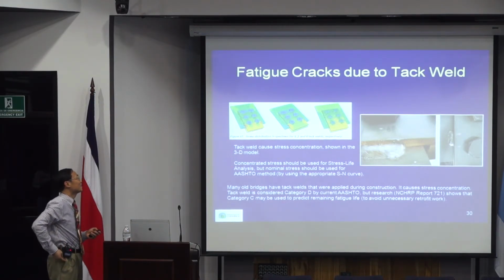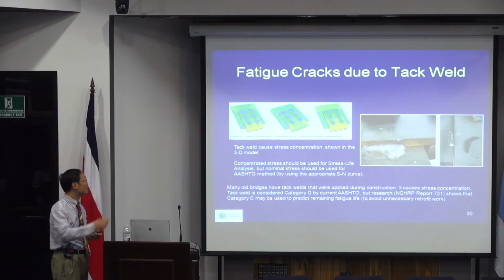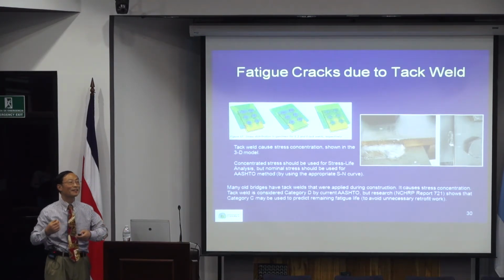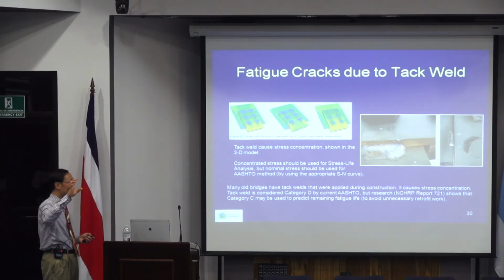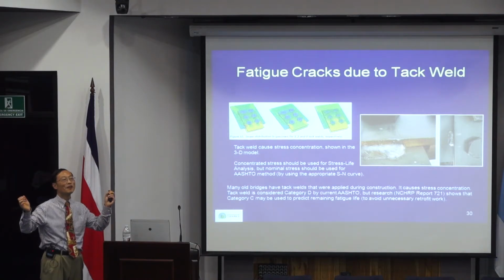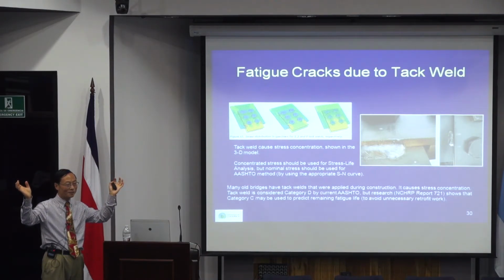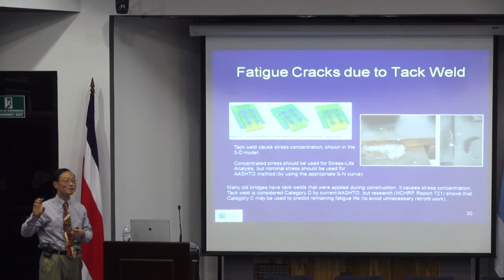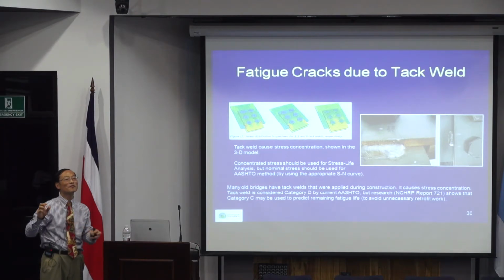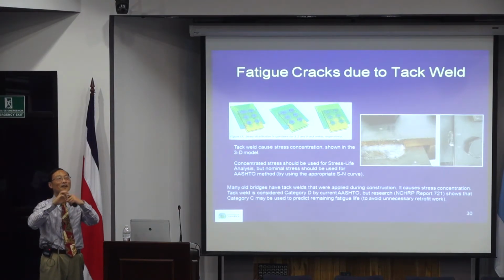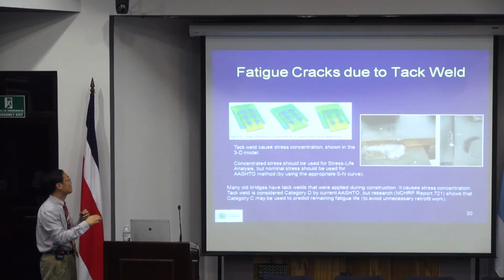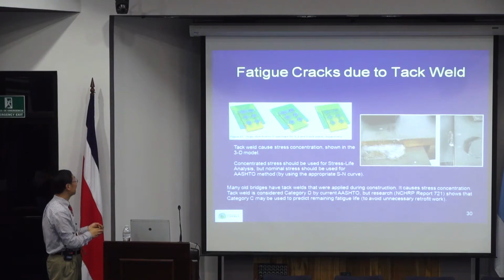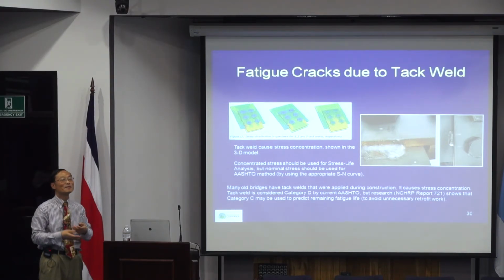Another thing, actually, it was not designed. We found a lot of problems of fatigue cracks. It's caused by what we call tack welds. Tack welds are when people do erections, they want to temporarily stabilize it before they do the bolting. Bolting is actually relatively easy. Before, there was no bolt, so people used rivets. They want to have these holes aligned because otherwise the holes will keep on moving around. So what the contractor did was they just tack welded these connections so that the plates will not be able to slide, so stabilize.